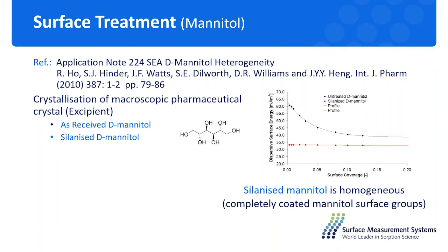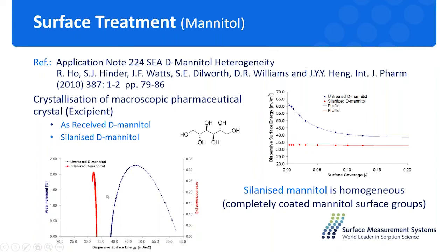And to get an easy interpretation of surface energy, we can also plot this distribution profile. So basically, we can compare the width of this peak: the blue line for the untreated mannitol is much wider compared to the red line for the treated mannitol, which is much simpler. The untreated mannitol is more heterogeneous compared to the uniform treated mannitol. And because the surface of this treated mannitol is more uniform and homogeneous, that also indicates that the coating of this mannitol with the functional group is a kind of complete coating, with all the sites on this mannitol coated with the same level of energy of the functional groups.